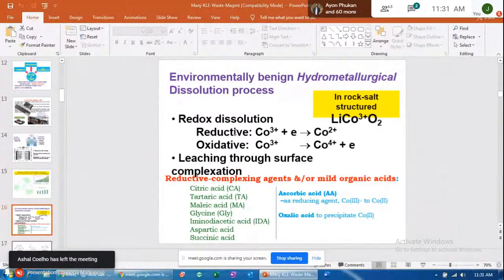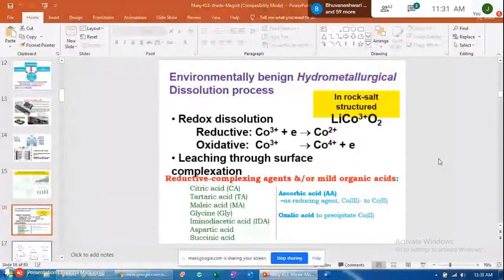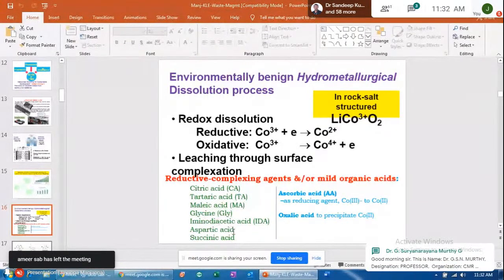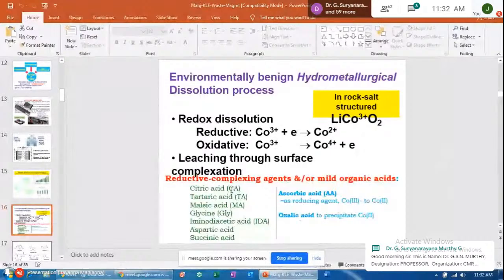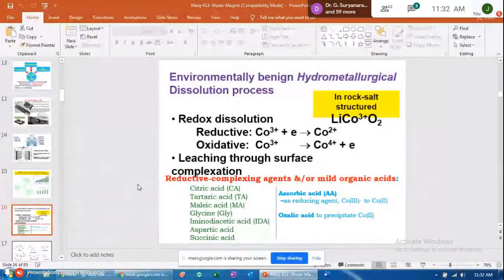Apart from that, simply using mineral acids is also a way to leach these materials, but mineral acids have their own problems. We want an environmentally benign process. So for reducing agents, I've listed many, like citric acid, tartaric acid, malic acid, glycine, ascorbic acid, oxalic acid. These are all mild organic acids which are environmentally benign. For example, ascorbic acid is vitamin C, isn't it? Using such things you'll be able to dissolve it and separate the cobalt and lithium as some precursors, which I'll describe in the next slide. Again, you can reuse those materials.